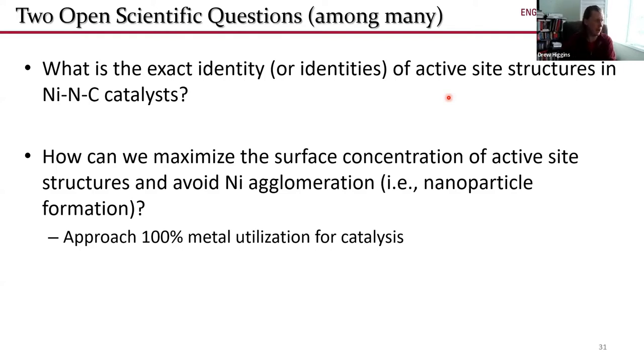And then the second question is, how can we maximize the surface concentration of these nickel active site structures and avoid the agglomeration of these nickel ions into metallic nickel, for example, that would not be beneficial for the reaction that we're targeting? Ideally, we want to maximize the surface concentration of these nickel ions, because that's how we can maximize the catalytic activity, and we can approach 100% transition metal utilization for the catalysis. Because once again, if we were to form metallic nickel particles, we're wasting a bunch of the nickel we're putting into the synthesis, and it's not doing the catalysis that we want it to do.